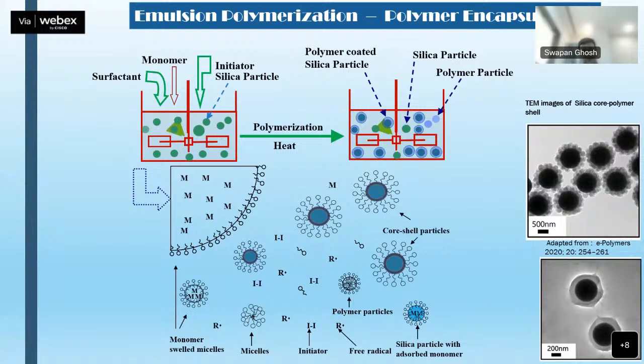But the criticality here is why in the previous slide I took some time. If you see the picture, almost everything remains the same. Only one factor will play a role here. There is now a competition. The monomers are in the micelles, the hydrophobic zone, but you also have silicon oxide particles. Now the question is whether the monomer would love to go to the micelle or to the silica particle, because if they go to the micelle, they will form free polymer particles. And if they go sit on the silica particle, then the polymer will be formed on top of the silica particles.